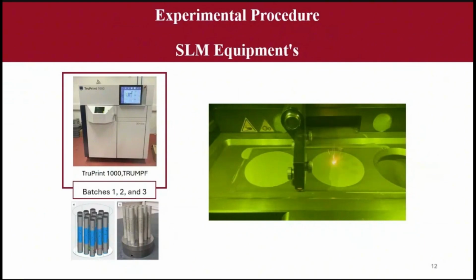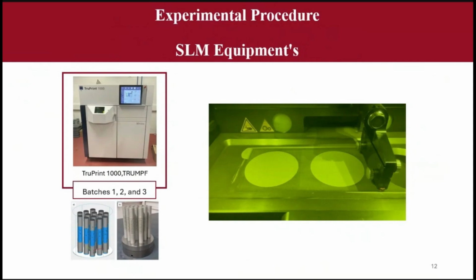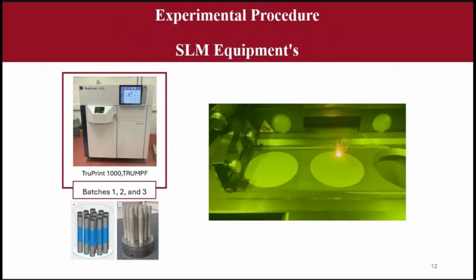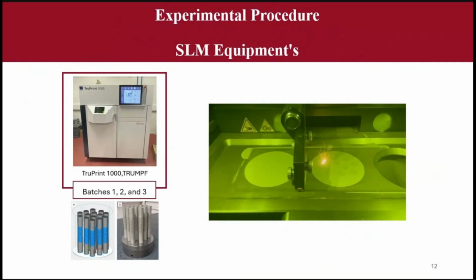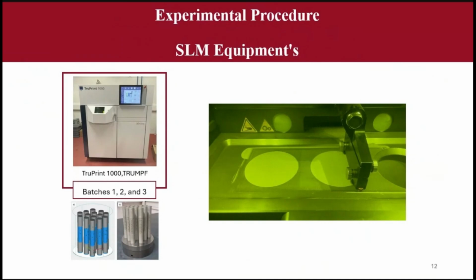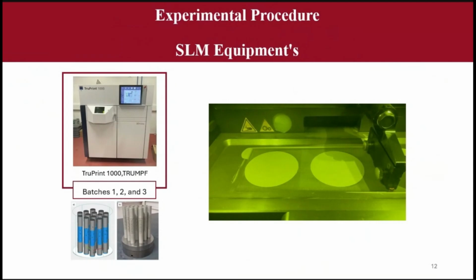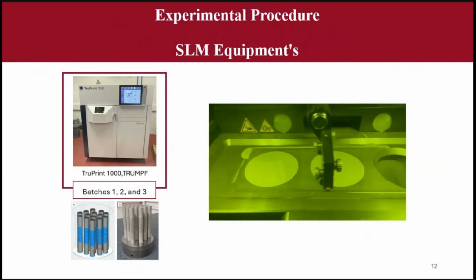So we produced these specimens with the printer equipment, and we produced 3 batches. Here is the film where we can see the scan of the powders and the laser doing the building of layers. The position of these layers is very important. Sometimes we have to put in some degrees of inclination to have a flux difference, but for this we made it vertical.